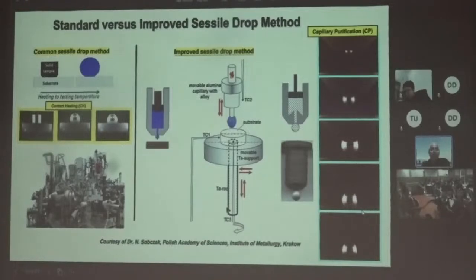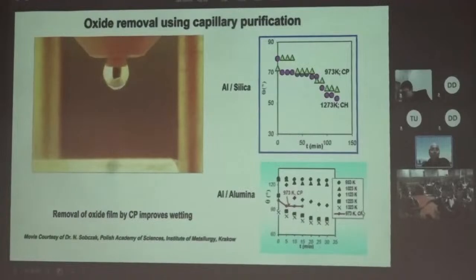Well, Dr. Sobczak has this special instrument where she's able to squeeze the little droplet on the substrate. In the normal sessile drop test, the solid is first brought in contact with the substrate and they are heated in contact. But the problem here is that you have no control on the time because interactions will begin right in the solid state itself. So if you want to study the liquid-solid reaction, this is not a correct approach. So what is done here is the solid metal and substrate are independently heated and at some time they're brought in contact. So this kind of a test allows a more scientific approach to wettability study.